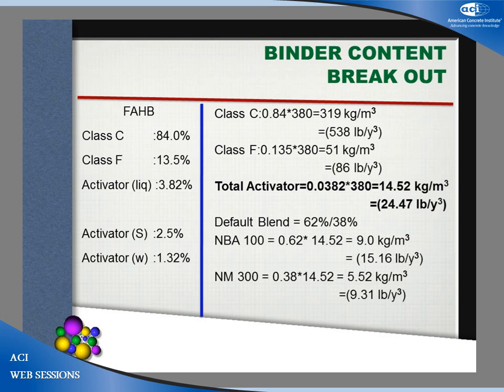Now we have the 380 kg per cubic meter binder content, and here is the default formula for the fly ash based hydraulic binder. So just get the breakup of each component. Class C, we got 319 kg per cubic meter. Class F, 51, and total activator, we got 14.52, and we have two activators, and the default ratio is 62:38, so we can also get the individual activator quantity in kg per cubic meter or pound per cubic yard.